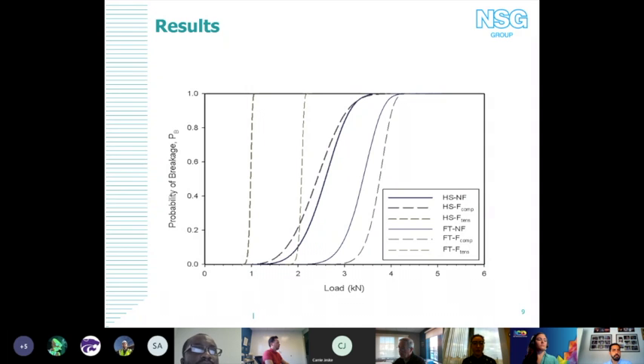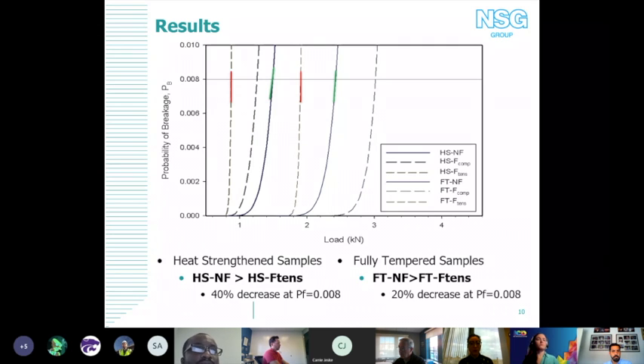So if we move forward to the next slide, you'll see focus down at 8 in 1,000. It's a lot closer when you get down to a probability of failure of 8 in 1,000, but we're still seeing a 20% decrease in fully tempered glass and a 40% decrease in heat strengthened glass once you start putting that fritted side in tension. And in some of the tests we did, we saw that the glass was fracturing at a stress lower than the recorded residual stress that we measured, which means that potentially the residual compressive stress on the fritted side isn't as high as it would be on the unfritted side.